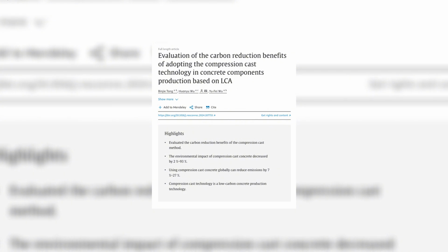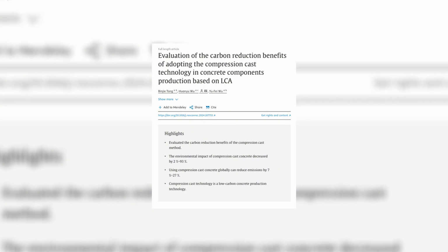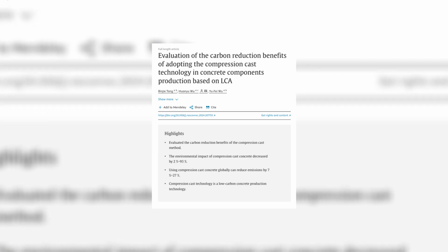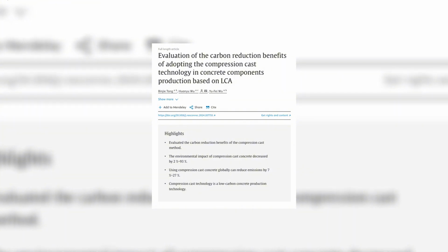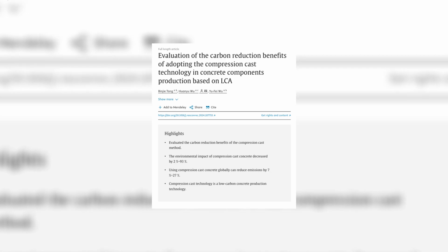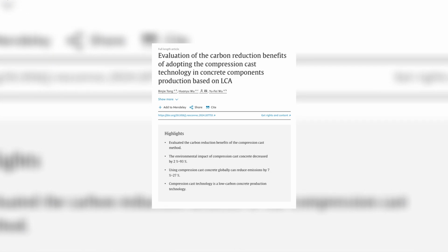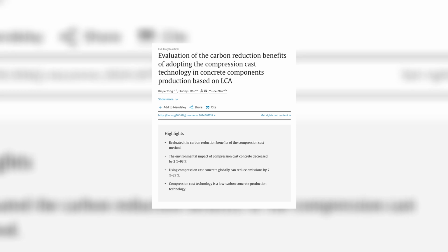A life cycle assessment published in 2024 estimated that compression casting could reduce carbon emissions per unit of compressive strength by roughly 21 to 45% compared with conventionally cast concrete. The same research modeled several hypothetical adoption scenarios. Under those models, replacing 25% of conventional concrete component production with compression casting could reduce annual emissions from the global concrete industry by around 7%. At complete adoption, the modeled reduction reached 27%.